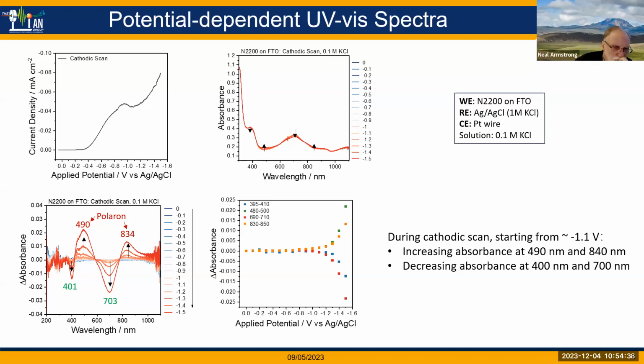And I think that's a really important distinction: is it only a small volume that's able to interact with the solvent because it's hydrophobic, and so the water is not penetrating down into the film, or is it islands of faster charge carriers associated with aggregates, and the amorphous fraction in plane is just not participating? That's an easy question to ask, and it's a really hard question to differentiate.